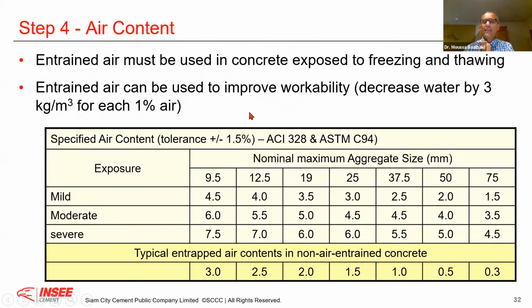Now, air content. As I said, very often you have to entrain air, but in our case we do not entrain air in Sri Lanka. We do not entrain air, or in India or in any country in this region, because we don't have a frost problem. Only if I go to North India probably. Now, for example, in Sri Lanka with a 20-25 millimeter coarse aggregate, I can consider between 1.5 to 2% of air in my concrete. Of course, every concrete will have a certain volume of air, like entrapped air. That is really what we can consider.